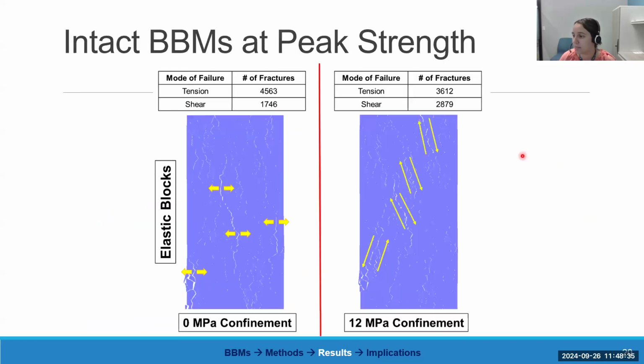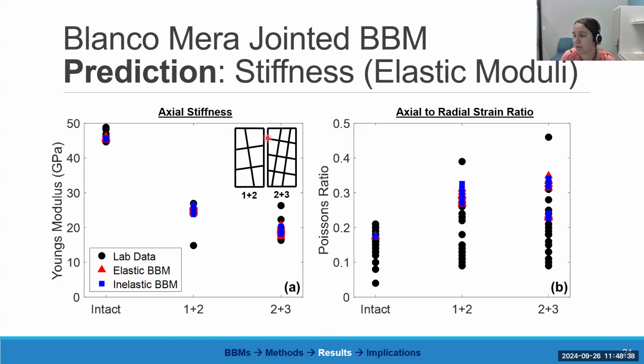And then for the jointed models here, the big joints are much less stiff, and they don't have any cohesion or tensile strength or anything like that. And actually the friction angle input for these large joints was measured directly in the lab as 30 degrees. Because the point of this study was that we calibrated the intact model, but we didn't want to calibrate any of the input parameters for these joints. So that's another reason we used smooth joints, because they've got 0 cohesion, 0 tensile strength, and we were able to directly measure that friction angle in the lab. Is that the whole question, I think? Yeah, and yep, shear and normal stiffness values for the contacts.